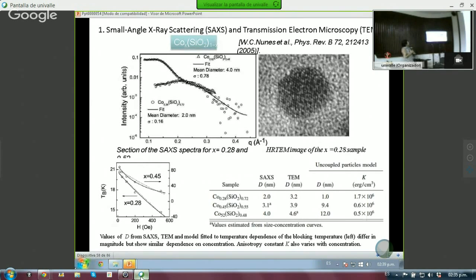Okay, so this is an illustration of small angle X-ray scattering. As you can see, on the right is the high resolution electron microscopy image, and on your left-hand side are the results of the intensity of the small angle X-ray scattering. You can make fits, and from the fit you can get the size of the nanoparticle, and in this case we got 2 nanometer with a sigma equal to 0.16.